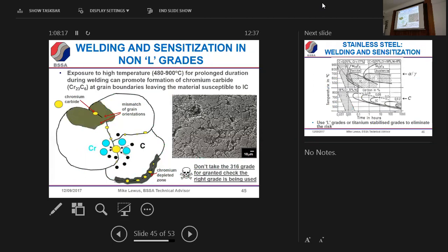Very quickly, carbon diffuses to grain boundaries and forms chromium carbide. That depletes chromium from the grain boundaries. Effectively, you've got a different grade at the grain boundaries because it's not as high in chromium. That's what we call sensitization. So if this chromium carbide is present after welding, the material becomes sensitized. If you then put that into an adverse environment, like a marine environment, it'll be prone to intergranular corrosion. The grain boundary is going to be attacked. So there's a very simple rule to avoid that.